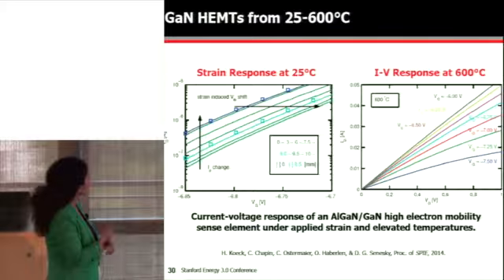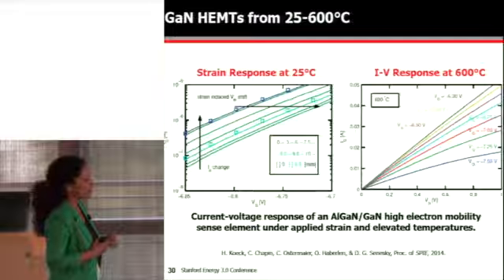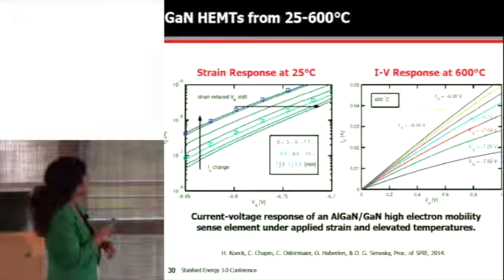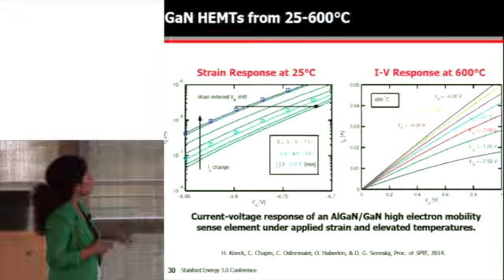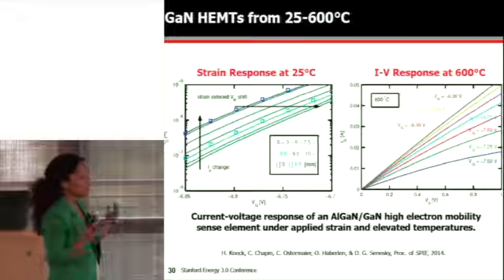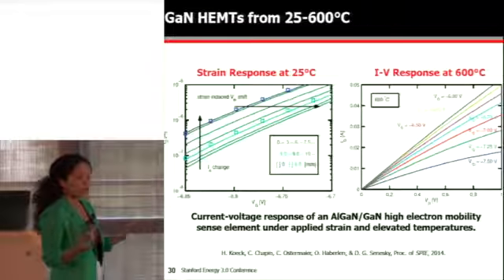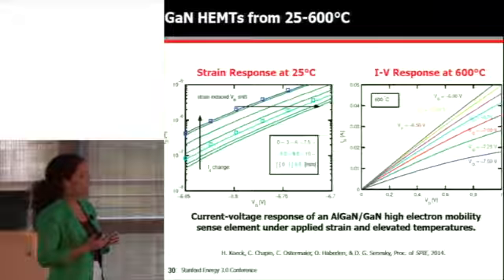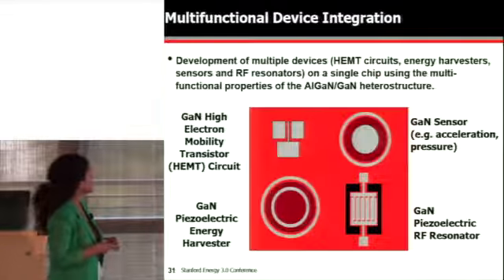This is the IV response of our gallium nitride sensor at room temperature, but under induced strain. You can see as we increase the strain, the blue curve is zero strain, and as we increase the strain, we actually get a different IV response. So we get a shift in the drain current and a shift in the threshold voltage due to applied strain. And we've also studied the high temperature response of the sensing element at 600 degrees C under different gate voltages. So we're again able to have a functioning sensor or transistor device at temperatures as high as 600 degrees Celsius.